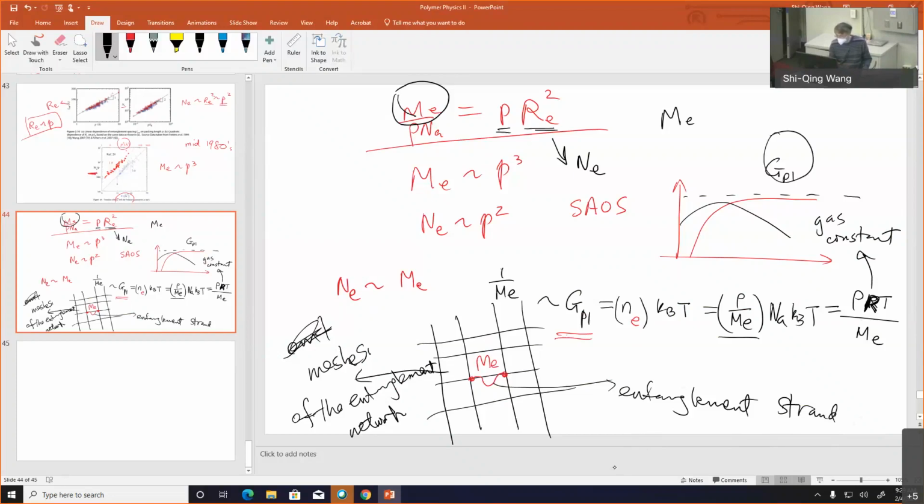So you make an oscillatory shear measurement to determine the plateau modulus and use this value to evaluate, because you know the density of your polymer, you know Avogadro's constant, you know at what temperature you made this measurement. You precisely know what is ME. And we have a tabulation of this value for all known polymers.